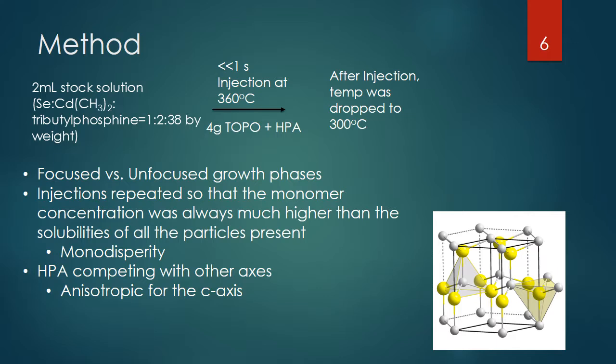During the growth phase, they started monitoring the reaction and found that there was a focused growth phase and an unfocused growth phase. They called them focused and unfocused because during the focused phase they were getting the growth they wanted — quantum rod growth instead of quantum dot growth.